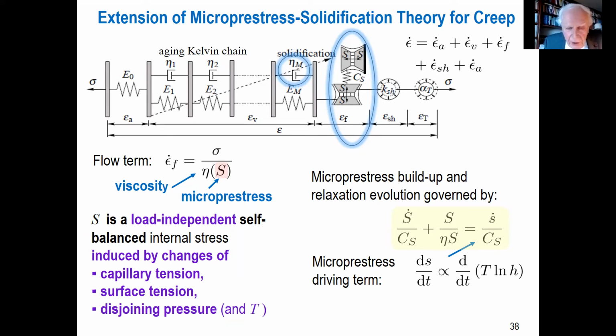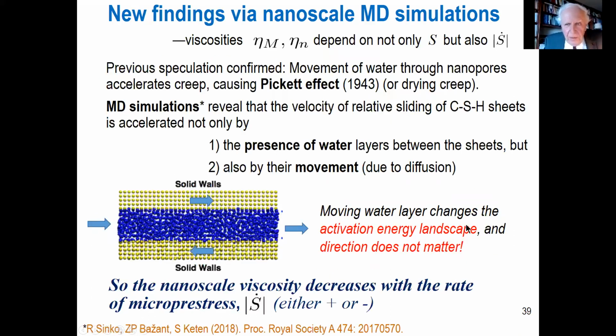And what is also an essential point is that micro-prestress is a local stress, self-equilibrated in small volumes. It's independent of external load. External load does not affect it, also cannot affect it. It's driven by changes of humidity and temperature. And now here I want to mention a point. At first, in the original micro-prestress theory, it was assumed that only the values of micro-prestress affect the viscosity. This is the viscosity of flow and the viscosity of the creep.